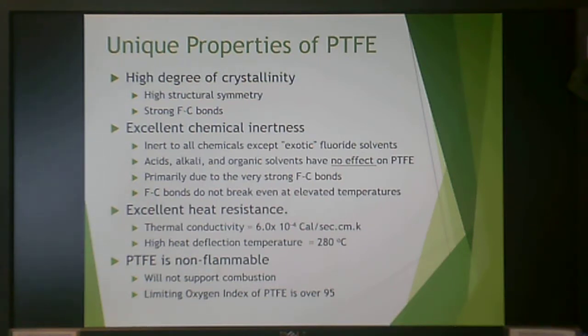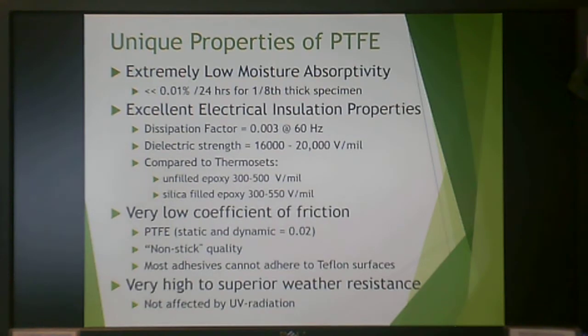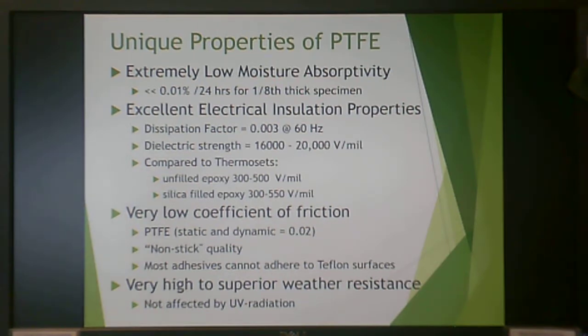Teflon also has excellent heat resistance — its heat deflection temperature is 280°C. It is non-flammable and will not support combustion at all. Its limiting oxygen index is over 95%, meaning you need almost pure oxygen to even force ignition. It has very, very low moisture absorptivity — much less than 0.01% over 24 hours for a 1/8-inch thick specimen, essentially zero. It also has exceptional electrical insulation properties — superior to even a silica-filled epoxy thermoset.